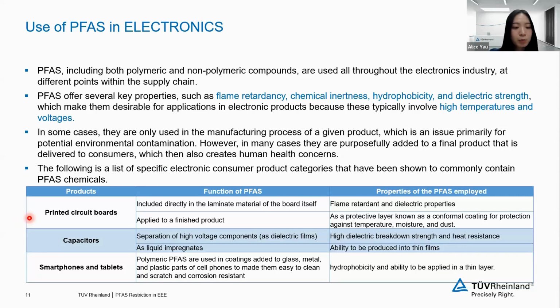For printed circuit boards, the PFAS is included directly in the laminated material of the board itself because of the flame retardancy and the dielectric properties. Also, it's applied to the finished printed circuit board as a protective layer known as the conformal coating for protection against temperature, moisture, and dust. For capacitors, PFAS can be used as dielectric films because of the high dielectric breakdown strength and the heat resistance.